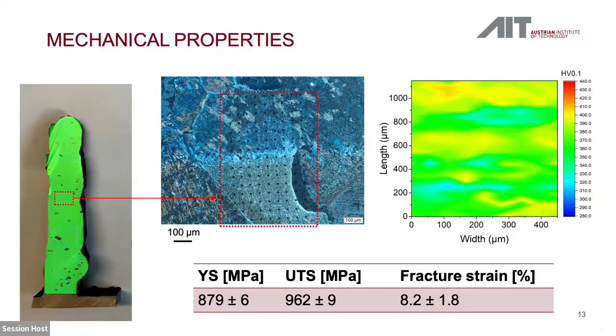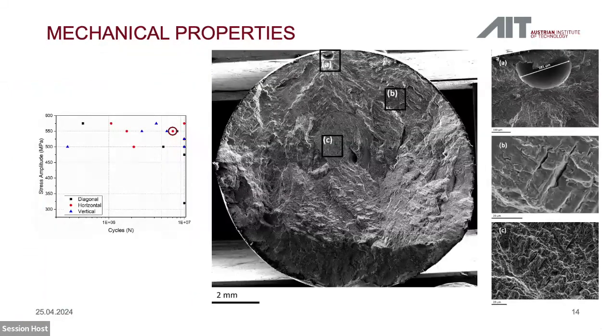Okay, finally, I would like to show you some of an ongoing study. We're looking at fatigue properties of the material. If you take a look at the graph on the left-hand side, there were samples extracted in different orientations of the build. You don't see a pronounced trend, which is good because there is no anisotropy in terms of fatigue properties. What is interesting to note is the fracture surface.